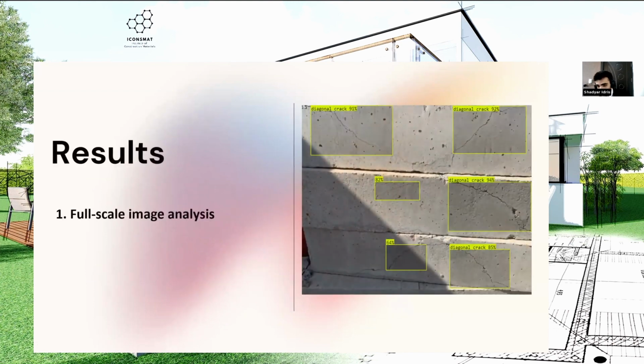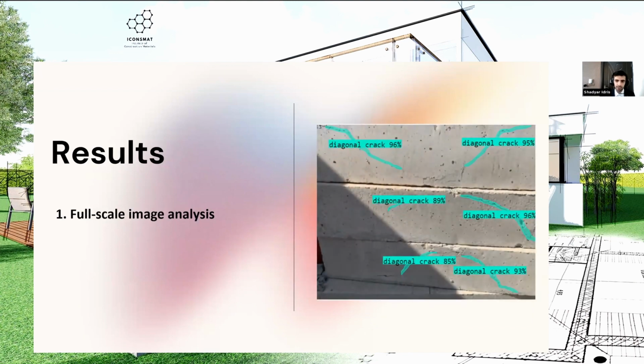I'm going to talk about results. This is an image of some prisms. As you can see, when I applied the model to it, it detected most of the cracks. It detects this diagonal crack, and it's 91% sure. And this is another diagonal. This is the bounding box model. As you can see, it only draws a bounding box around it, nothing more. But when we look at instance segmentation, it draws the exact shape of the cracks, and this can be very crucial to some industries or work.